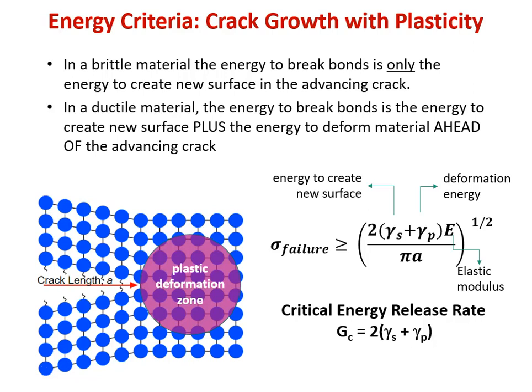You might ask yourself, why is this limited? I mean, if it's a ductile material, ductile materials can accommodate 20, 50% strain at failure. Why such a small deformation zone? Remember that right at the tip of a crack, we actually have a triaxial stress state. It's very, very constrained. So unfortunately, we can't get a lot of plasticity. So that plastic deformation zone is actually pretty small. But it will also vary with the material as well as with the geometry of the crack. So the more ductile the material, the bigger that plastic deformation zone will be for any given crack geometry.